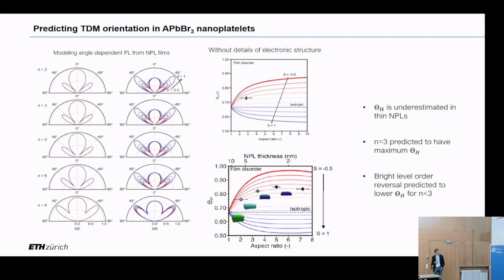And if we don't consider those details, we severely underestimate this parameter. And also, we can see a strange effect which has to do with the bright triplet level reversal, is that very thin platelets below n equals 3 have an anisotropy parameter which is lower than thicker platelets, which is counterintuitive. Why? Because the out-of-plane excitons now are energetically favorable.